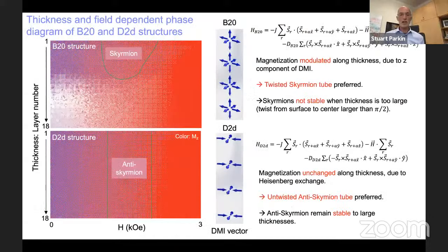Now this is in complete contrast to the anti-skyrmion. This is very nice work by Zhengbing Ma in my group here in Halle, who explored this using micromagnetic simulations. He changed this code, the OOMMF code, so we can have any type of symmetry of the Dzyaloshinskii-Moriya exchange vector. And he compares on the top the B20 structure, the iron germanium or manganese silicon system, which shows skyrmions. And I don't know if you can see, but basically from the top to the bottom, 1 to 18, these are increasing thicknesses of the structure. Each of these layers is tens of nanometers thick. And you can see going from left to right is the perpendicular magnetic field. So the skyrmions are stabilized in a small region of magnetic field and thickness.